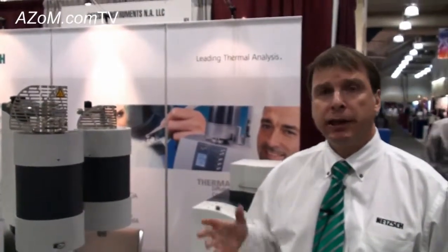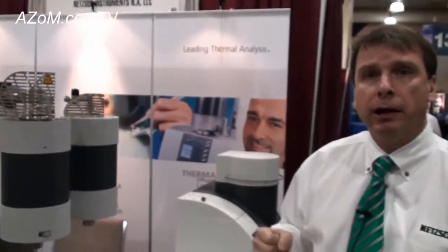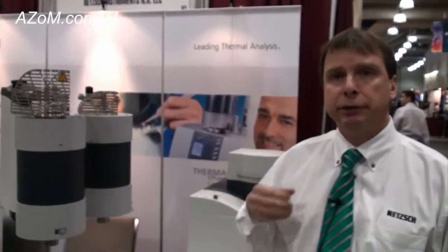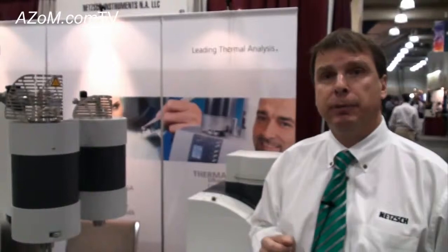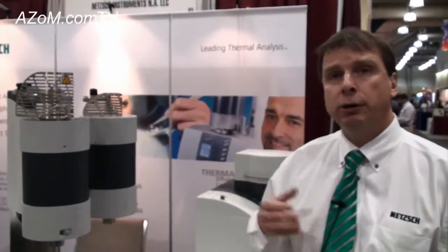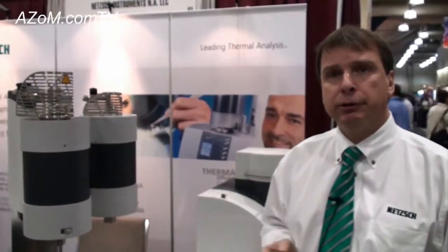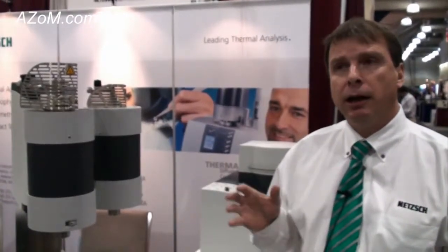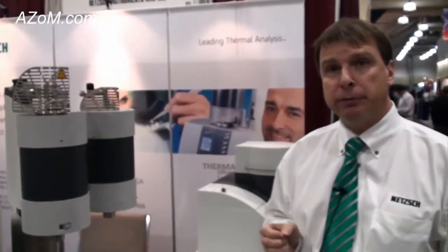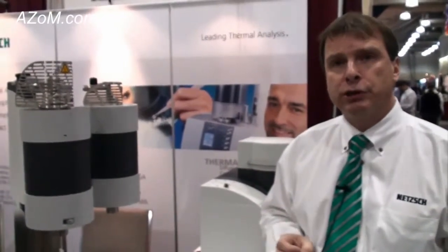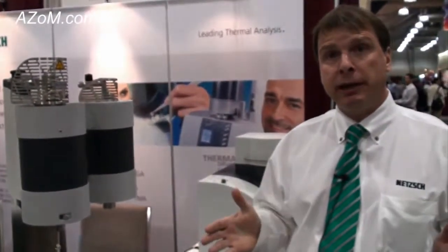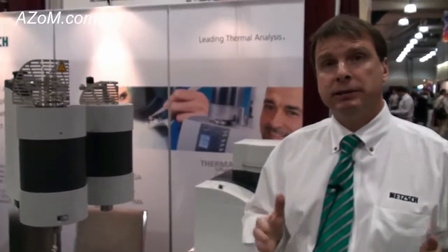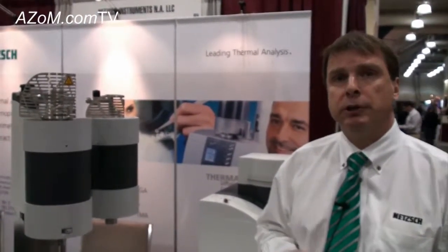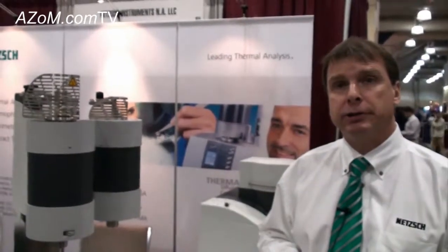Well, a lot of our customers in a high temperature field use it for studying of ceramics, the sintering process, also in metals for looking at phase transitions and melting points of metals. But also, even in the polymer industry, we can do the simultaneous DSC TGA, and we have that unique characteristic of being able to measure from -150 up to 1,000 in a single run, which if you're using separate DSC and TGA, most independent DSC instruments only go up to about 600 or 700 degrees Celsius.